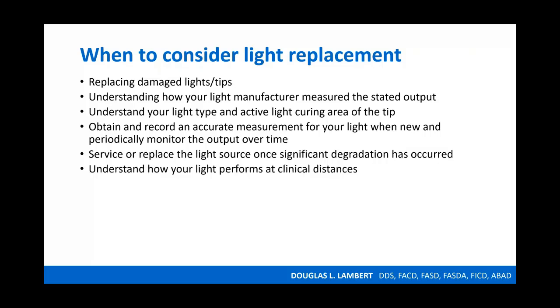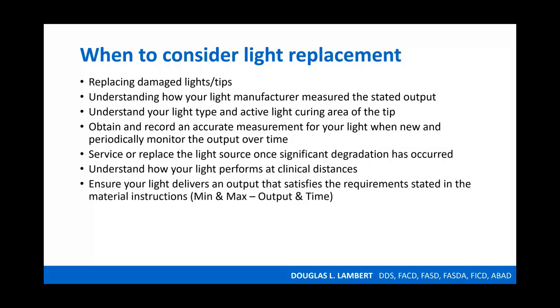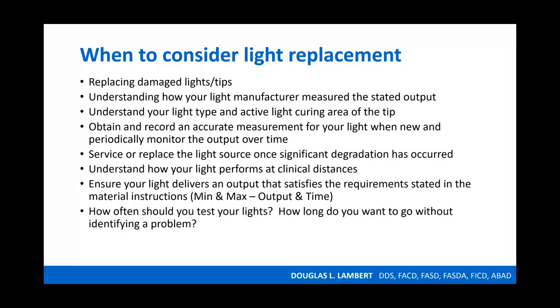Now, when you see degradation has occurred, when it's dropped below a threshold that you're comfortable with, 1,750 milliwatts, it's time to replace the light. You want to understand how your light performs at clinical distances, and how much irradiance you're losing at 1 millimeter away, 5 millimeters away, 1 centimeter away. Make sure that your light delivers an output that satisfies all the requirements stated in the materials that you're using. And how often should you test those lights? I'd say, how long do you want to go without identifying a problem? Test them every day if that makes you feel better. Test them every week, I'd say, is probably your minimum. Otherwise, you get something that you really don't want to have happen.